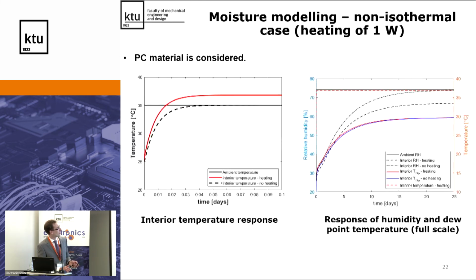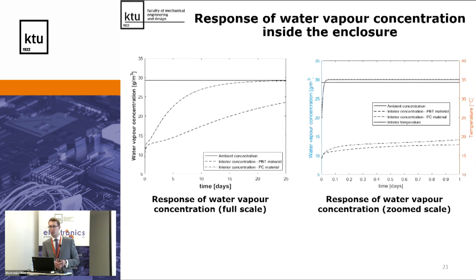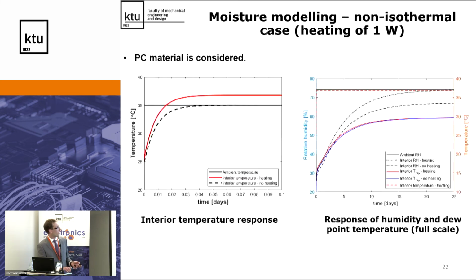And so to imagine how big the difference is, polycarbonate material at 20 Celsius temperature can absorb up to 5 kilograms per cubic meter of water vapor, while air can contain only 17 grams per cubic meter. So we can see a big difference in how much moisture solid polymeric materials can absorb compared to the air.